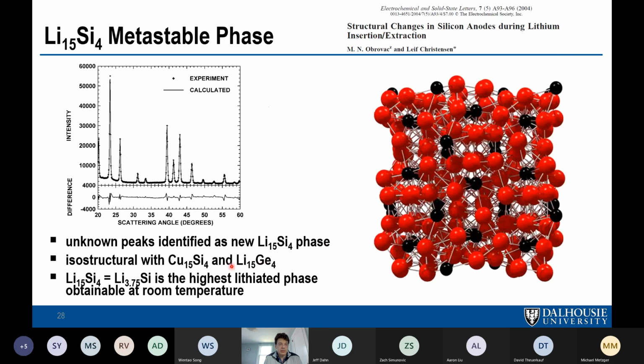And so we had to figure out what it was. The way we figured it out was, okay, let's compare to other silicon alloys, and it matched almost exactly with copper 15 silicon 4, and later we found it matched with lithium 15 germanium 4. This 15-4 stoichiometry is the closest packed arrangement of different size spheres. So it occurs quite often in intermetallic compounds, but it hadn't been observed before in the lithium silicon system. This is only formed at room temperature.